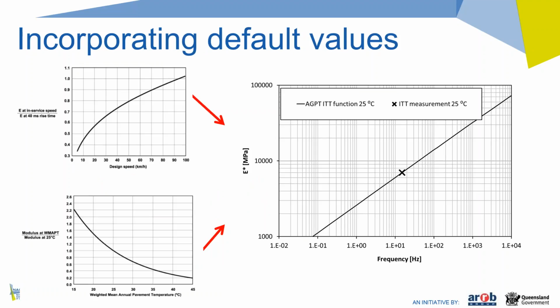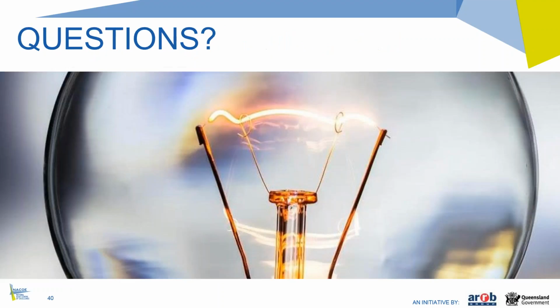Actually, we show that bottom asymptote as well. So we haven't cut off the 1000 MPa in that example. When we send out the technical note, you'll be able to look at one of the figures in there to see exactly what Eric's saying about the asymptote being symmetric at both ends. And to answer David's question a little bit further, the asymptote is typically between 200 and 500 MPa if you're doing laboratory testing.